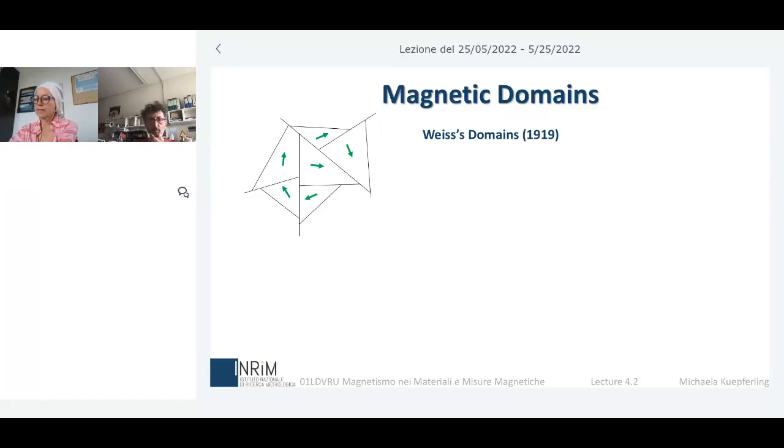No? If I then attach another iron clip to it, then they will stay together even if I remove the field, because now the domain structure will be completely modified, and we have a different domain structure that allows these clips to stay together. So domain structure and domains are very essential in order to describe the behavior of my magnetic material. Otherwise, without domains, I cannot understand the behavior of ferromagnetic materials.